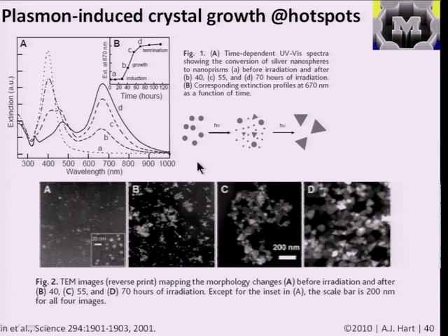And then they're like, well, what's going on? Because typically when we make our structures, we don't see a different color happening. And what it turned out is that the interaction between the fluorescent light and the silver ions and small clusters in solution caused growth of these triangular shaped prisms. And as the prisms grew, you observed this size dependence effect on the spectrum, and you saw peaks appear and disappear and the peak position change.